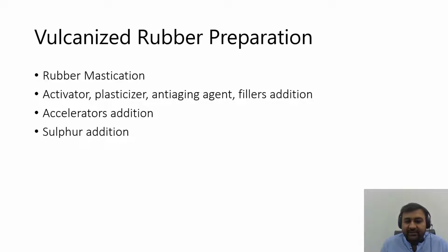So in general, the vulcanization of rubber comes in 3 to 4 steps. Rubber mastication is done for approximately 15 to 20 minutes, and then activator, plasticizer, anti-aging agent and fillers are added. In the third stage, accelerator is added, and in the last stage, sulfur is added for vulcanization of the rubber.